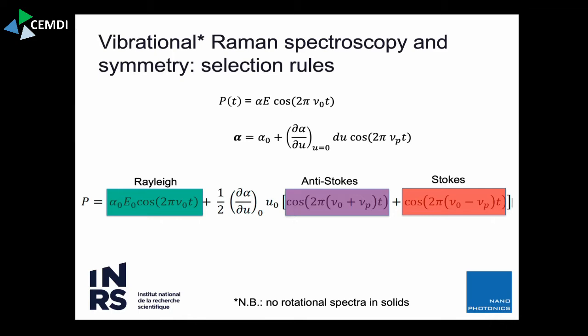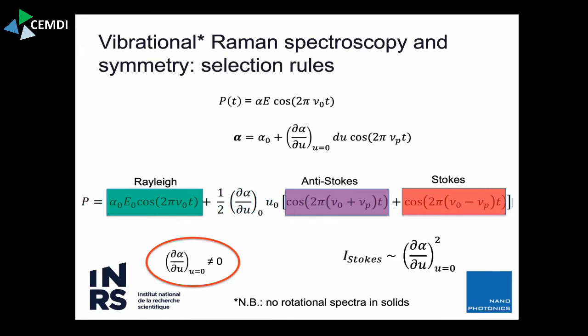And usually I'm discussing that part here. Today, I'm not so much interested in that part. I'm focusing a little bit more on that one here, which is the so-called selection rule. So obviously, because this is a product here, this fellow has to be non-zero to make sure that you get a Raman effect. So this is the selection rule to say, I need a change of polarizability for very small deviations from my equilibrium position. What that means, I'll come to that in a moment with an example. And just as a reminder, if this one is non-zero, then the intensity of my Stokes line, the one we usually observe, scales with the square of this, because that's actually the electric field intensity with the square of the electric field, so that small change will actually become detectable.